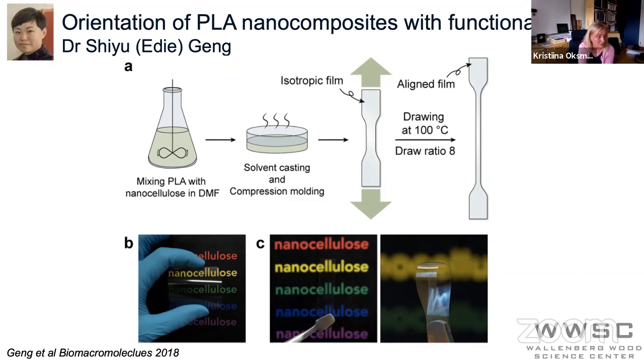And this work was done by Dr. Shiyu (Edie) Geng, and this was one project financed by Wallenberg Wood Science Centre. And in this work, Edi made grafting of nanofibers with polyethylene glycol. And we know from before that this improves the dispersion of the nanomaterials in PLA. So our idea was to make a composite with very, very good dispersion. And she made those composites with solvent casting, and she made drawing at 100 degrees, and she managed to have as high a draw ratio as 8 on these materials. And you can also see here that the films are transparent before and after the drawing.